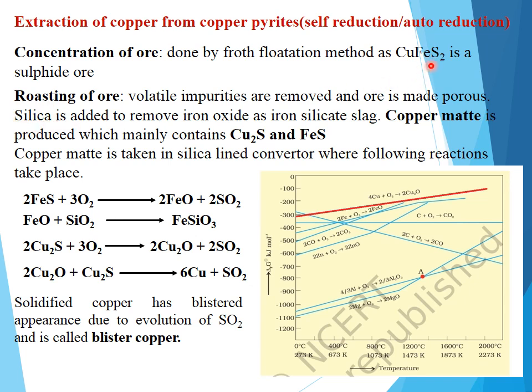So first, sulfides of iron get oxidized due to roasting and convert into ferrous oxide, and that ferrous oxide combines with silica to form slag, which is nothing but iron silicate slag or ferrous silicate slag. The left out mixture is called copper matte, which mainly contains cuprous sulfide and ferrous sulfide. A small amount of ferrous sulfide is left out, and this mixture, the copper matte, is taken to a next container called the silica lined converter, where the following reactions take place.